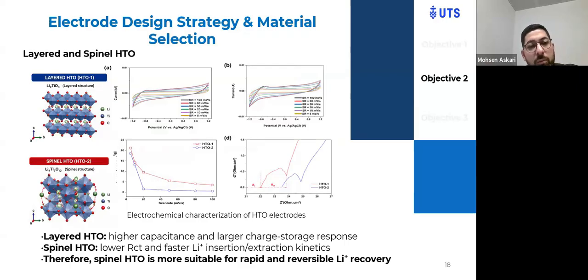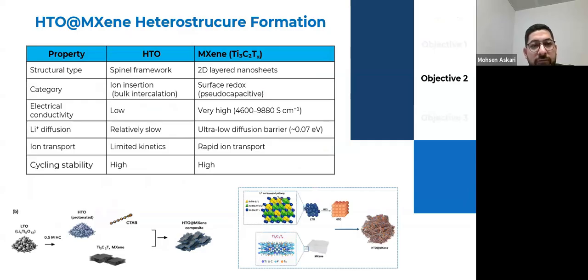Based on this, we first compared the layered and spinel structures of the HTO based on the electrochemical test. The layered HTO shows higher capacitance and a larger charge storage response, while spinel HTO shows a lower Rct and faster lithium insertion and extraction kinetics in EIS. Therefore, the spinel HTO is more suitable for rapid and reversible lithium recovery and was selected for our next experiment. So we have the HTO-MXene composite prepared based on this procedure, and we expected to have the selectivity and high lithium uptake rate with this composite.